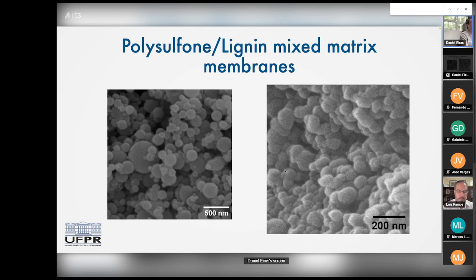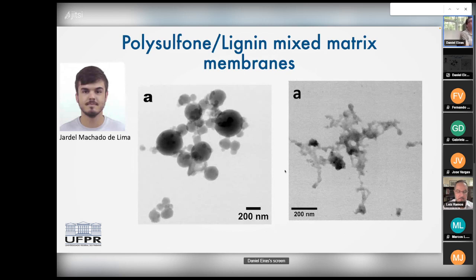So you can see clearly that we can get spherical particles with THF, but we cannot get something very spherical with DMF. This has to do with the solubility of lignin in those solvents. That one was an SEM result. Here I have a TEM result that confirms that the THF particles are spherical, while the DMF particles have an elongated morphology, a different morphology than expected.